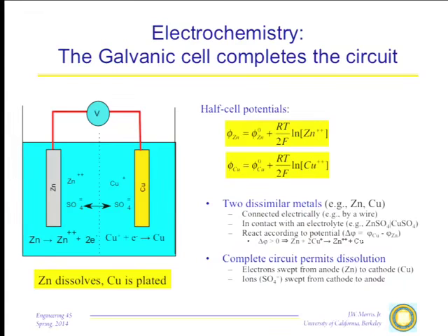Now, if there were no water here, that process itself would go on just a little bit and then it would stop, because you get an accumulation of charge over here in the copper, and that would fight the addition of more electrons, and your current would stop. But now let's suppose we have them in contact with an electrolyte. Zinc ionizes, goes into solution, releases two electrons. The electrons run over here to the copper. If there's copper in the solution, then the electrons in the copper can now combine with the copper ions to produce metallic copper, and that consumes the electrons. So now we have a circuit. Electrons are flowing from zinc to copper, ions are flowing through the solution, and the whole thing is in electrical balance. So the potential difference between the zinc and the copper never goes away, and this can just keep going and going until all the zinc or all the copper is consumed.